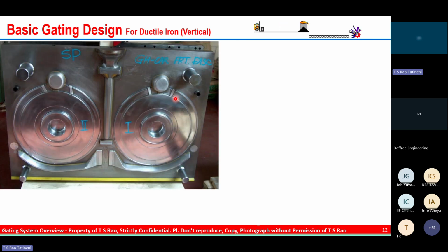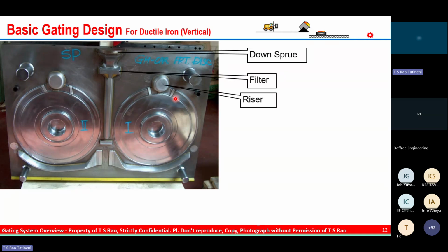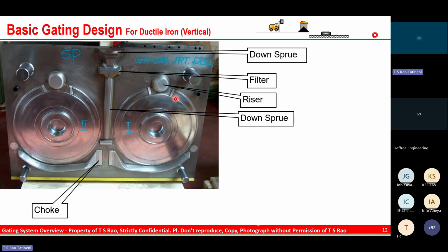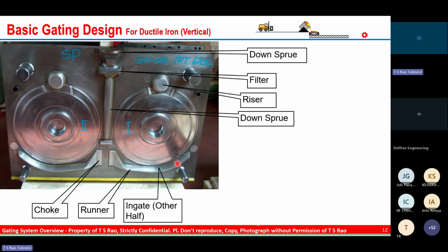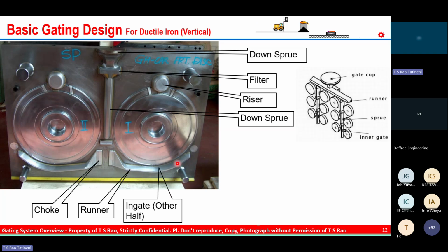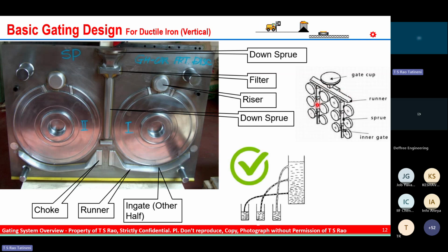When you see the vertical casting process, it is again vertical green sand molding. Here, instead of cope and drag, we have SP and PP. But here the orientation would be different. Here the down sprue is at the top, followed by the filter and the risers on top of the casting cavity. And there are chokes here and the runner bar, then followed by the ingates. Normally the ingates are given in other halves. So if you see the typical layout, the cup here and then followed by the runner, then there are multiple cavities within the vertical molding.